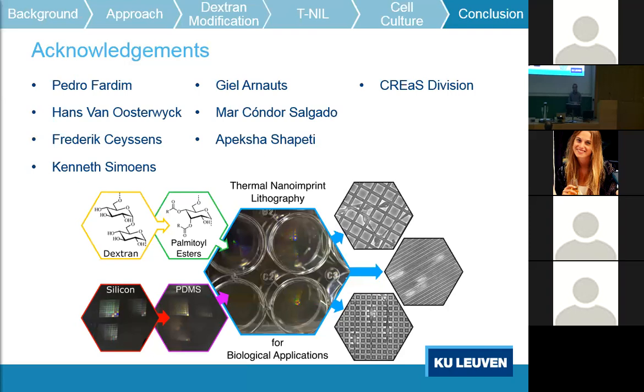So how handleable is that? If you want to detach the film and roll this up, is that something that you could do in an upscaling approach? Is that feasible? First you would need to begin with patterning of a much larger structure, of course, not these little glass discs I have. But you can remove these effectively through capillary force. If you dip the glass slowly into an aqueous medium, it can peel it off if you do it precisely. So you could effectively peel off a sheet of this. That's interesting.